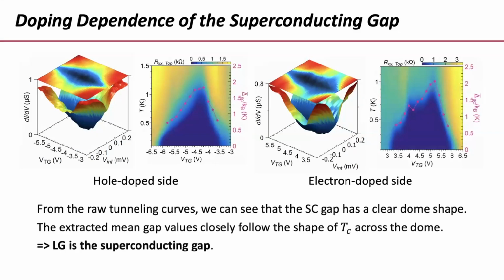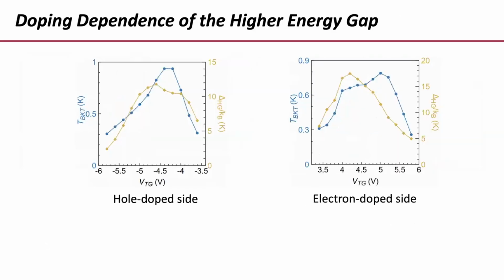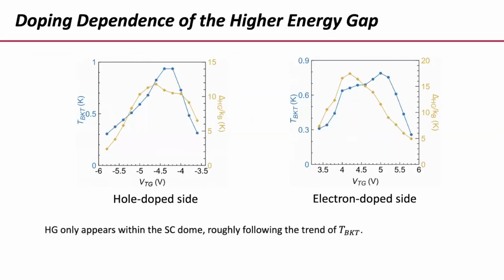Okay, I'm sorry I'm going so fast through this, but we can, of course, do all of this electrically dependent and check the dependence of the superconducting dome, and it's all consistent. Both the high energy gap, the pseudogap, and the superconducting gap have a doping dependence which has the same trend as the superconducting dome, okay? So most likely the high energy gap is connected to superconductivity, even though it's not the actual superconducting gap as established by phase coherence in the system.